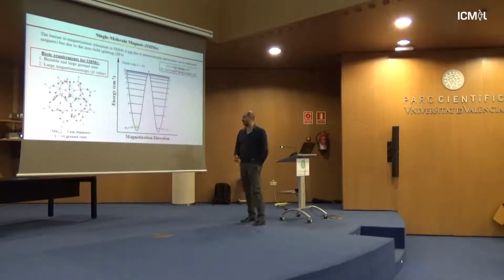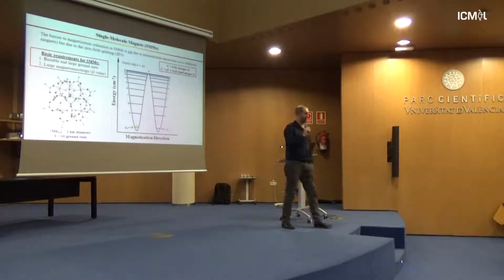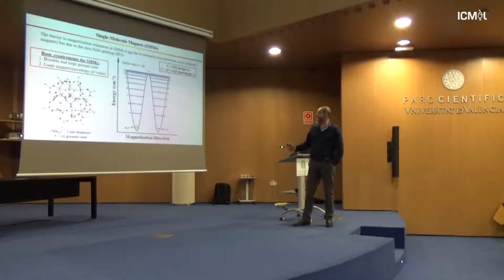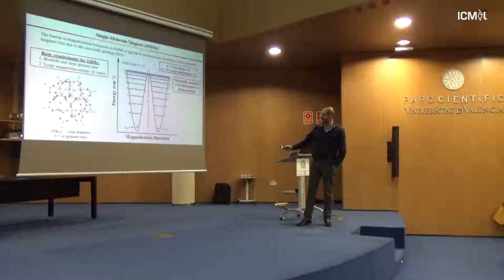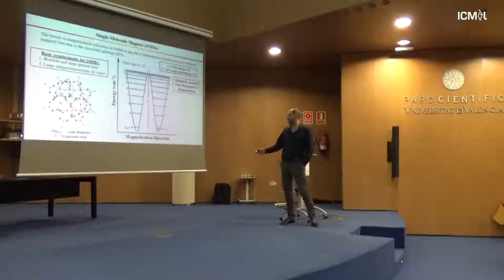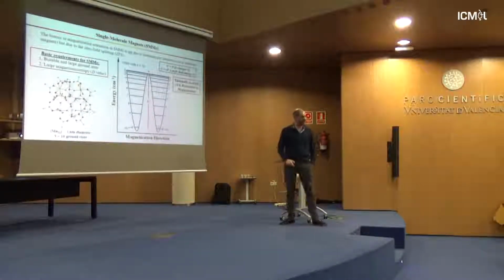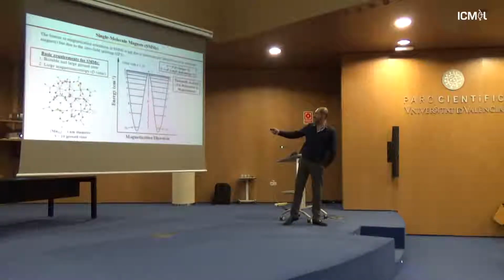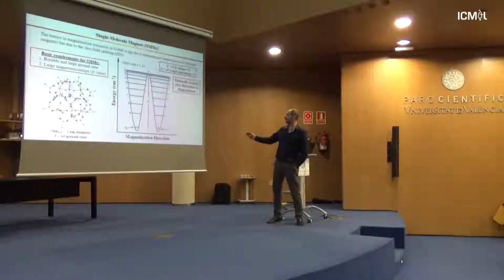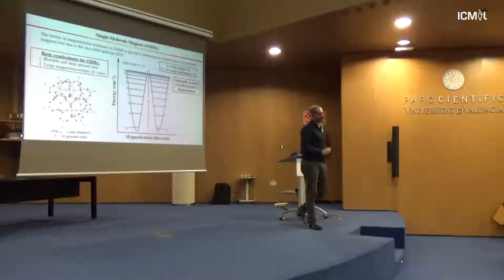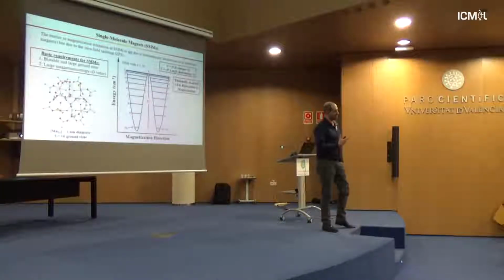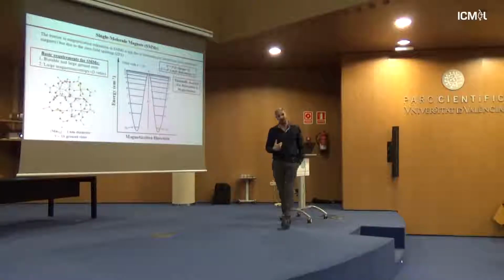But the three mechanisms for the relaxation of magnetization in 3d transition metal single molecule magnets will be shown here. The first, and the mechanism that we all would really like to have, is the thermally assisted process, where the magnetization goes over all of these microstates and relaxes over the barrier to the MS state with the opposite sign. This process gives you the maximum U, which is given by the two formulas here for integer and half-integer spin systems. This is called the thermally assisted relaxation. Now, is this very rare? It's extremely rare or impossible in transition metal single molecule magnets.